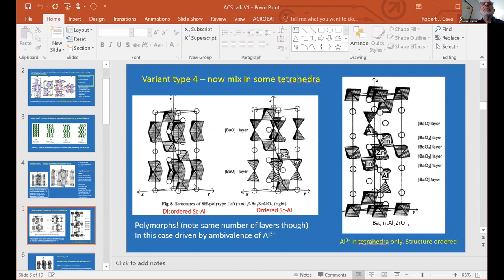It's Ba2ScAlO5. And this thing can either make a hexagonal perovskite that has dimers of face-sharing octahedra or dimers of corner-sharing tetrahedra. They are polymorphs of each other. They have the same number of layers per cell, but they're polymorphic. So this is a sweet thing, because aluminum oxides are bizarre. I mean, aluminum is a lovely element in the periodic table because it doesn't know whether it wants to be in an octahedron or in a tetrahedron. And so here's an example where it just doesn't know what to do. So it makes different polymorphs that have different coordination polyhedra for aluminum.